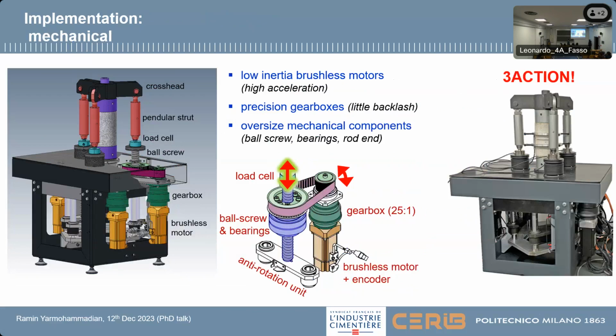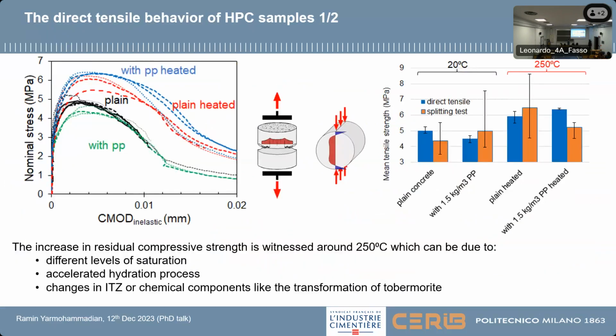And this is the outcome. So with the low inertia brushless motor, which has really high acceleration, a precise gearbox, and with all of those, we came up with the machine which we called 3Action. And this is now available in our lab. And this is the first result. So for the high performance concrete, as you see, we could get good repeatability, even if the concrete is very brittle. In normal concrete, it's really easy to get it. But when we are dealing with high performance concrete, this falling branch is really steep. And in the normal condition, you cannot get it. So as you see, we could get all of those falling branches. And another advantage of this new test setup is that when we are done with our sample and we pull the samples apart, we're going to have 2 samples for splitting. So we can also test them in a splitting test to compare all of those with each other.